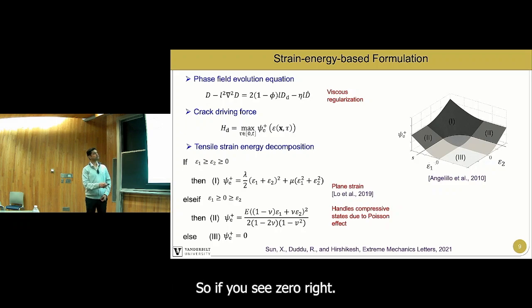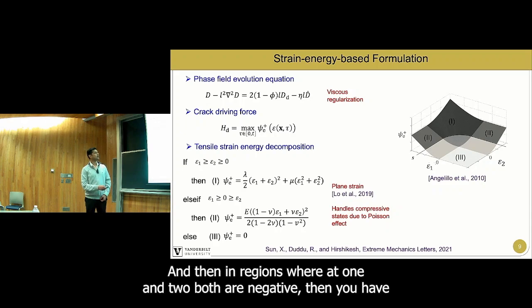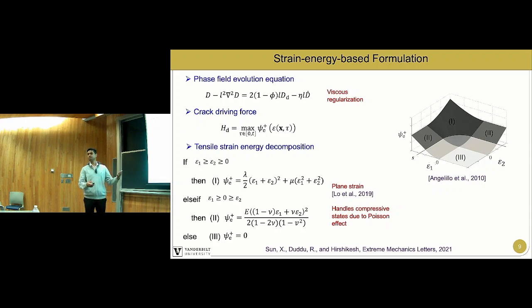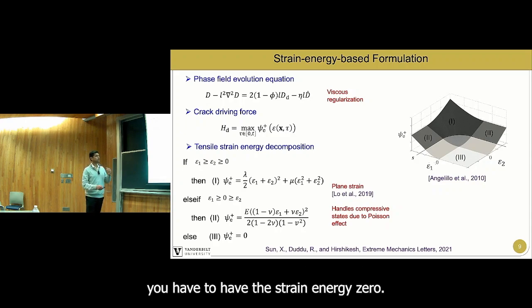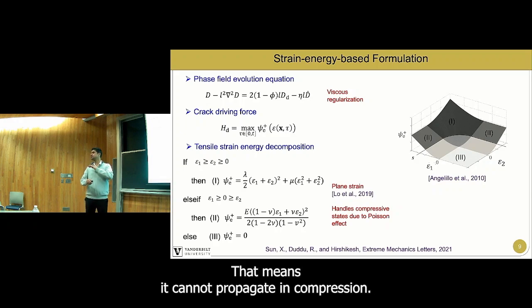And so you need to model regions 2 based on this when one strain is positive but the other strain is negative. So if you see 0, right? So this strain is, let's say, negative, but this strain is positive, and in that region it has a different slope. And then in regions where the 1 and 2 both are negative, then you have to have the strain energy 0. That means it cannot propagate in compression.